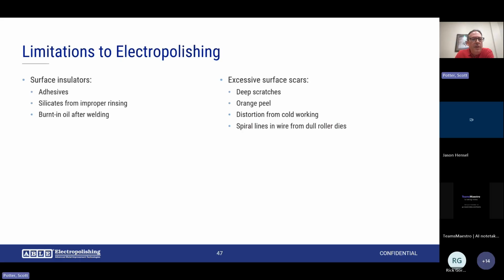Limitations of electropolishing: we do rely on good current flow for the parts for the process to remove the material uniformly. We typically don't like things like adhesives, silicates from improper rinsing, from maybe a tumbling operation prior to electropolishing, or burnt-in oil after welding. Typically with adhesives, one of the problems we run into is people buy vinyl coated materials. They peel the vinyl off, but then they leave this adhesive behind, which is very difficult to see. It can cause problems with conductivity with our process, and you get actual resist patterns.